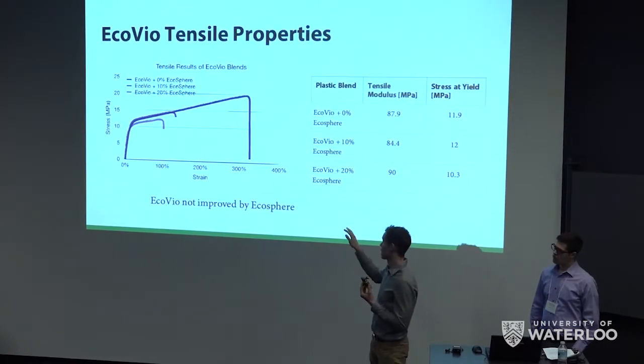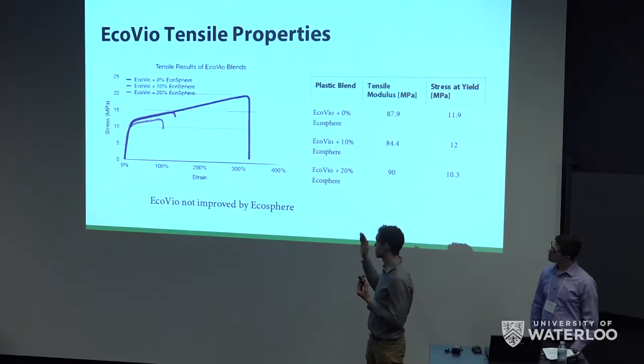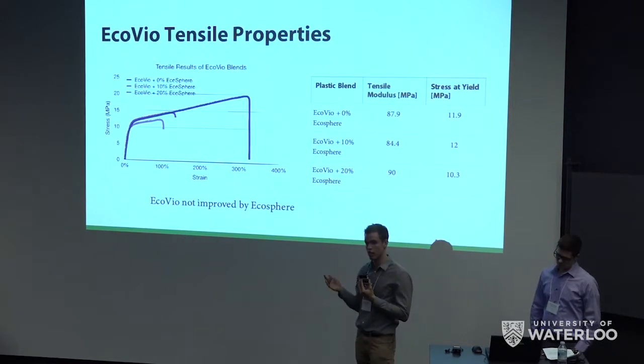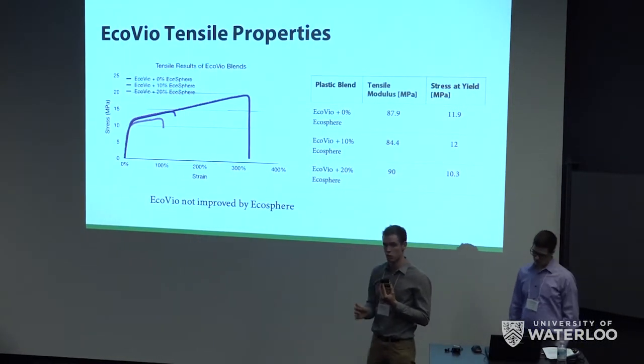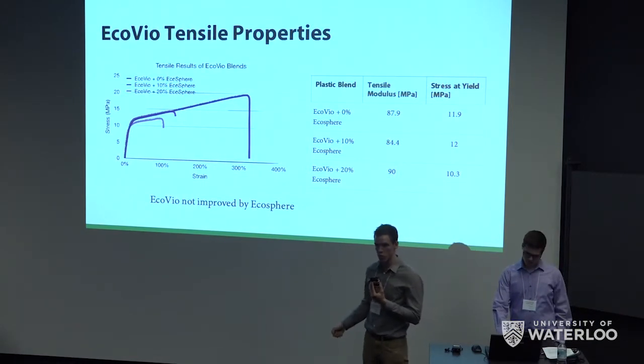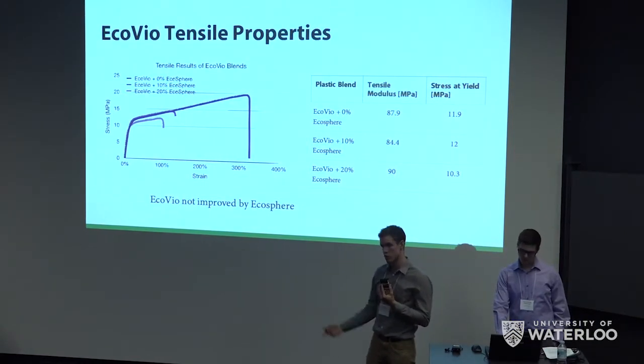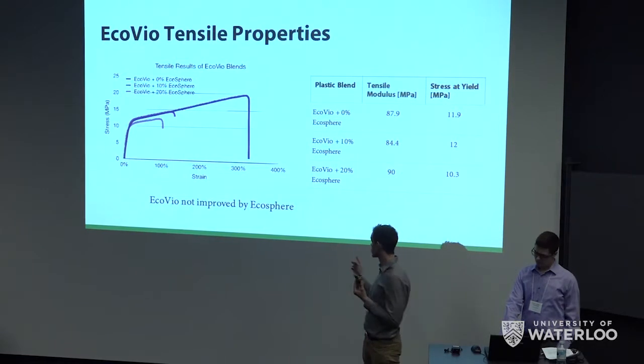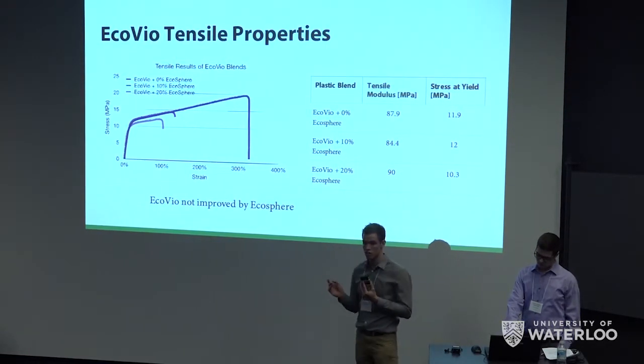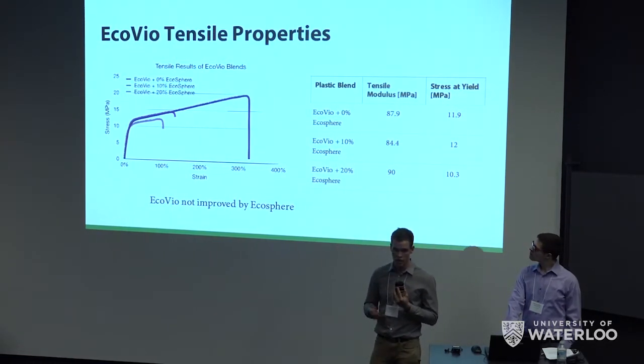And you can see in the plastic region, adding EcoSphere significantly decreased the elongation at break, but this is unimportant because if your plastic bag starts stretching more than 20%, you can't use it because it's going to be dragging on the ground. From this, we concluded that EcoVio did not properly blend with our filler, so it was not a viable option moving forward.